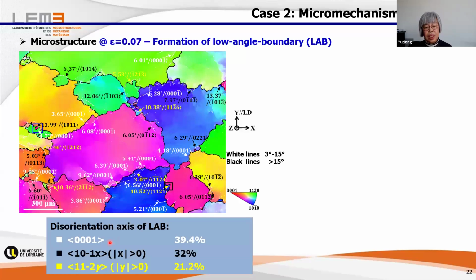And this we already know corresponds to the prismatic slip. But we have another two axes, and they have a large population. You see, it's one third of the population for this axis, and for this axis we have a quarter. And so, in fact, for such boundaries, the x and y values are not fixed. They range from 0 to 1, something like that.